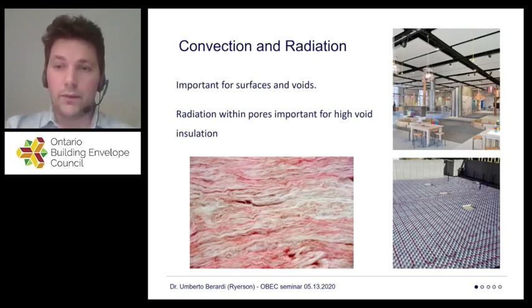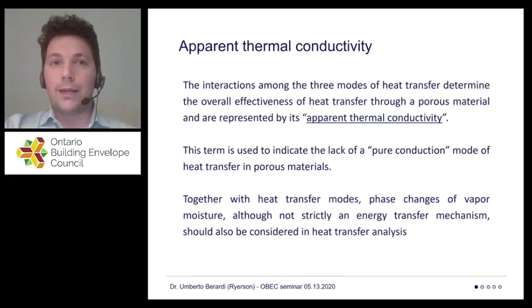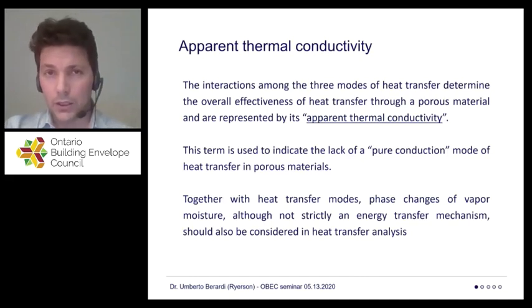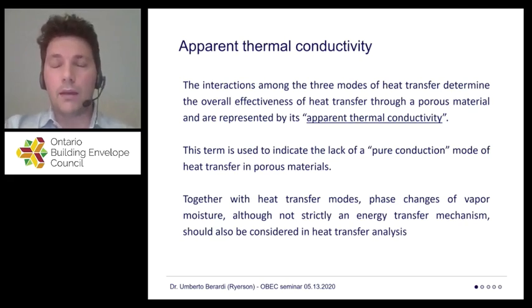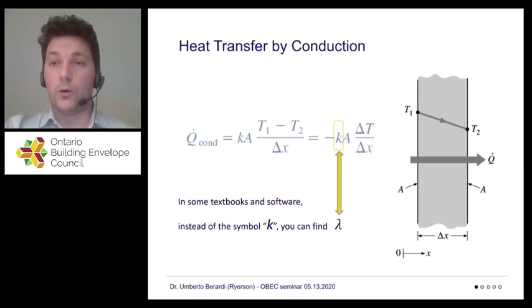And insulating companies know this very well, and they try to work ways to cut as much as possible heat transfer by convection and radiation that otherwise will occur also in an insulating material. So first of all, instead of speaking about a thermal conductivity as a property that is just reflecting the heat transfer by conduction, we should probably start thinking about the apparent thermal conductivity as a better definition of a behavior of a layer that has been allowing heat flux mainly through conduction, but also it's going to allow some heat flux through convection and through radiation. So basically, we never have a single heat transfer mode isolated from the others. And especially in a porous material, we have a lot of the different heat transfer modes altogether.